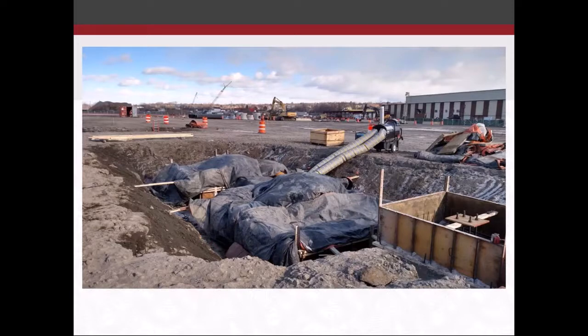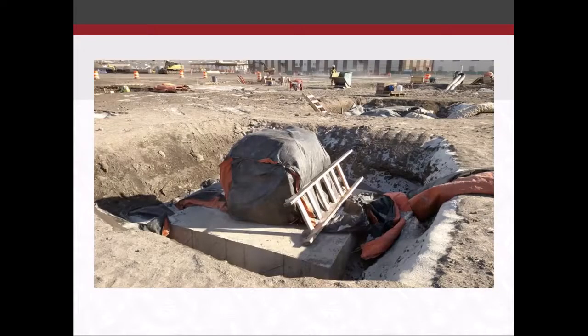This contractor was very well prepared. It was in the single digits when I was out here. These pictures were taken over the course of probably two to 3 weeks. Yeah, it got pretty cold. Here's a pier that was placed. You can see it's got multiple layers of blankets stacked around, tied up really well. These corners are really susceptible to freezing and thawing or getting exposed to freezing. So they got the corners tied up really well. Basically, they just took the blankets that they were using for this footing and moved it up there.